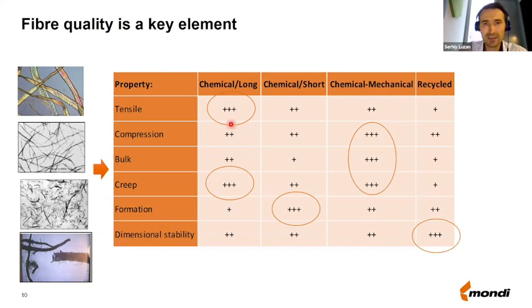And I just put a circle around the most prominent feature of every type of fibers. So for instance, softwood kraft fibers, or chemical long fibers, are particularly good in the tensile properties and creep properties. The hardwood chemical or hardwood kraft fibers are very good when it comes to formation. That's why, for instance, when you produce white top kraft liners, normally you put white hardwood fibers on the top and long chemical fibers on the bottom to get a good combination of strength properties and formation.